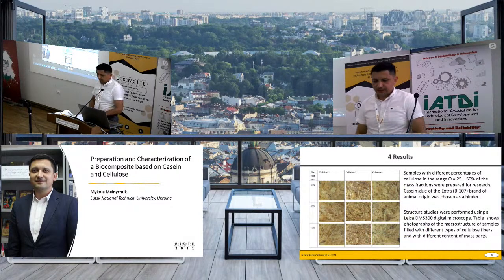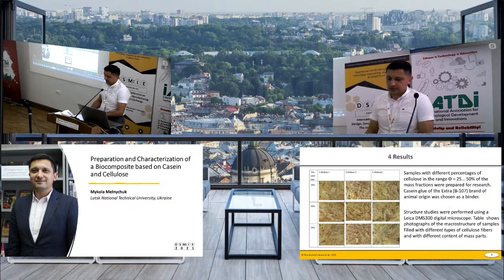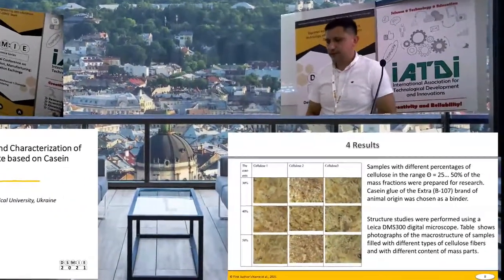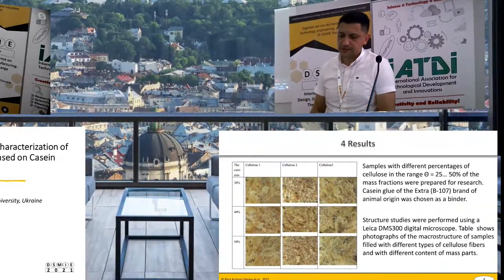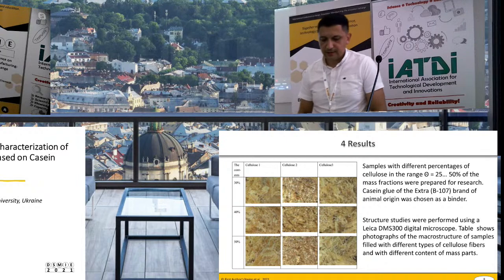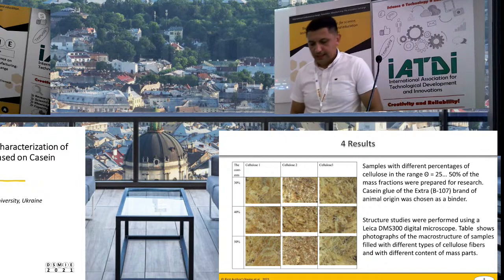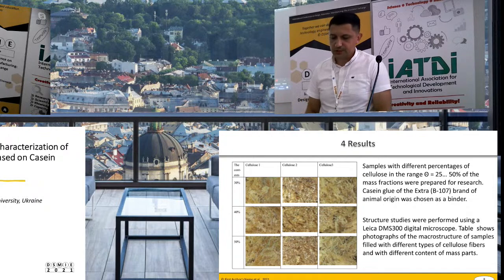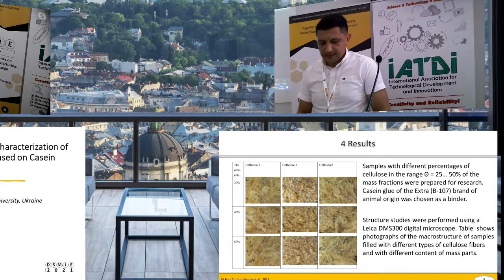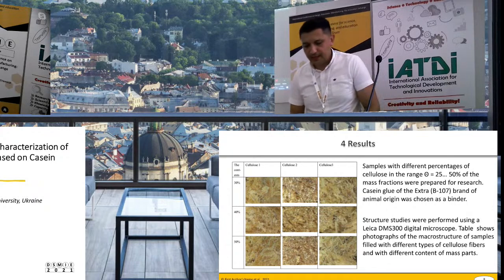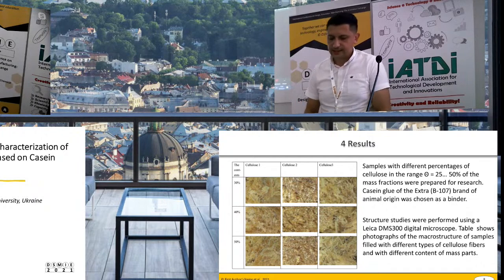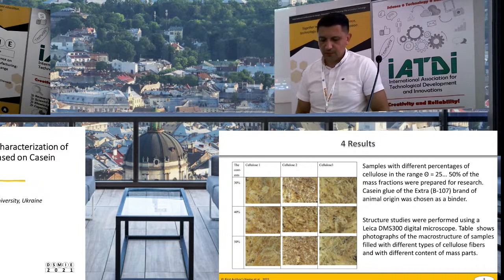Samples with different percentages of cellulose, in the range from 25 to 50% of the mass fraction, were prepared for research. Casein glue of the extra brand was chosen as a binder. The adhesive is characterized by high reliability for gluing wooden surfaces. It has no harmful emissions, so it is suitable for production of environmentally friendly composites.